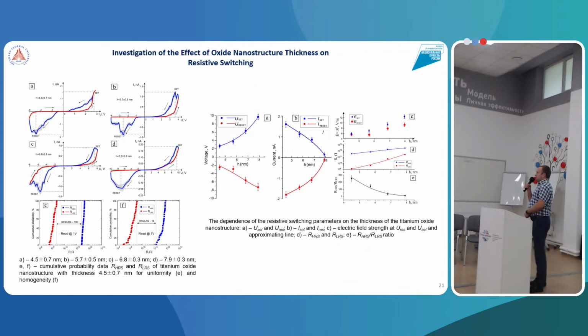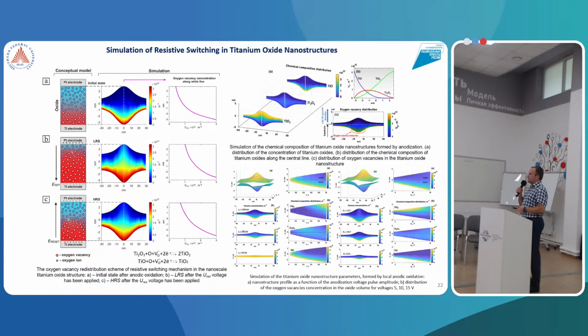We investigate the size effect, the influence of the thickness of titanium oxide on resistive switching processes. Here we see the dependencies of resistive switching parameters on the thickness of titanium oxide. We explain the physical mechanism.